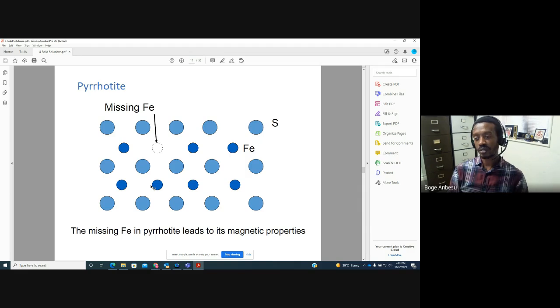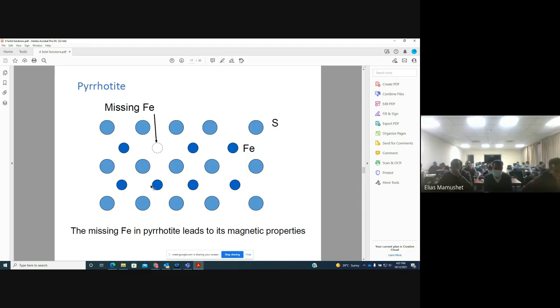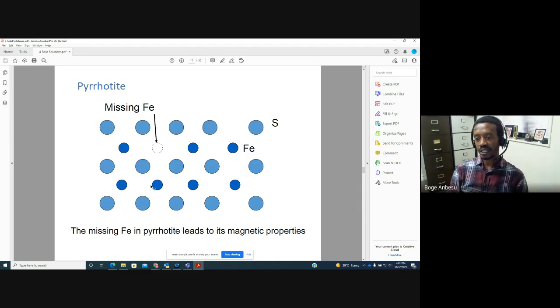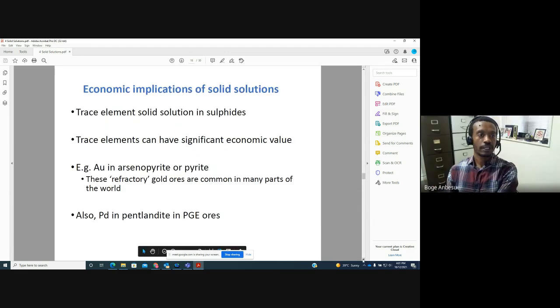And this is very important in processing because pyrrhotite is highly magnetic, and it's highly magnetic because the dipole moments for sulfur cancel one another, but for iron you have 1 iron missing, so there will be a net dipole moment, and that will make pyrrhotite highly magnetic. Those from geology can use this magnetic property of pyrrhotite for exploration purposes and so on. But the fact that it's magnetic is mainly due to 1 iron missing from its structure.